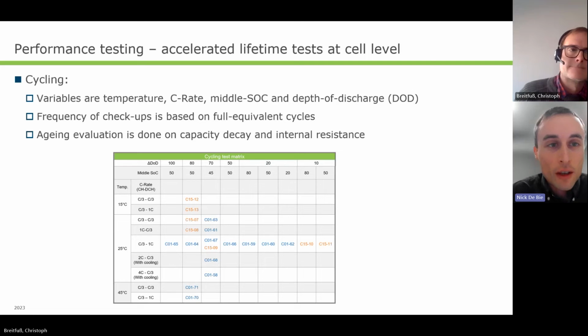With respect to the accelerated lifetime tests, the first type of test is the cycling tests. There we are using different variables: the charging rate, the mid-SOC, the depth of discharge and the temperature. We also defined and are executing periodic checkups based on the number of full equivalent cycles that the cell has done. These are divided in short checkups, but also more detailed checkups. With respect to the evaluation of the aging process, we do this based on the capacity decay of the cell relative to 100%, and the same for the internal resistance. So we use two evaluation criteria to evaluate the current aging process. On this slide, you also have a quick view of the test matrix that we are doing within Liberty.